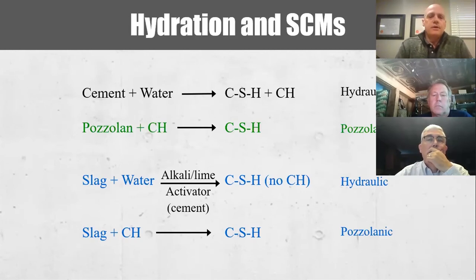Now, slag is a little different. It's not really a pozzolan, or has very little pozzolanic action. It is actually cementitious, but it needs an alkali lime activator, which is produced by the cement hydration process. So it does produce CSH, no CH. So that's a good thing. And then there's a little bit of pozzolanic reaction that does create more CSH. That's why these materials work. It's not just that we're replacing cement. It's actually reacting with the byproducts of cement hydration that makes them so valuable.